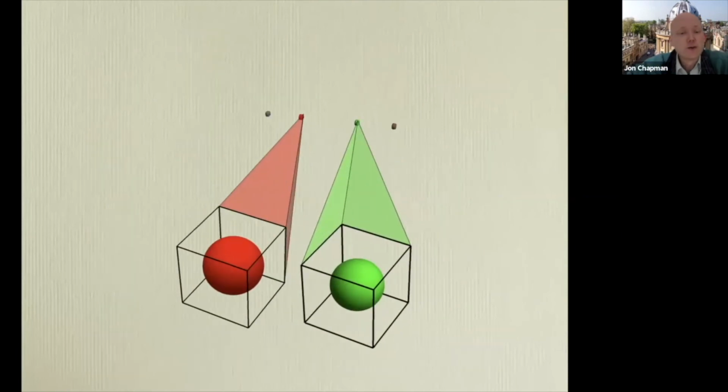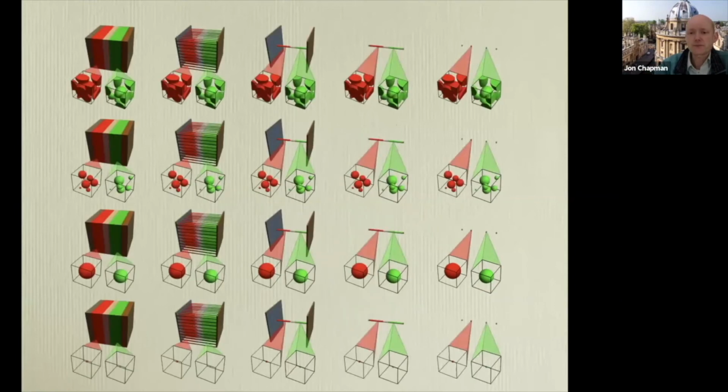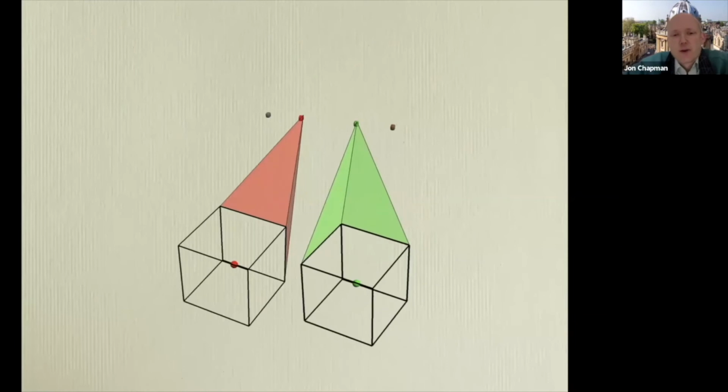I have a single representative spherical particle in the anode and a single representative spherical particle in the cathode. And if I go right down to the bottom right here, then I've got ordinary differential equations everywhere. I have a single ordinary differential equation for the anode and a single ordinary differential equation for the cathode. And you're getting to the stage of sort of equivalent circuits here, at least in terms of complexity.